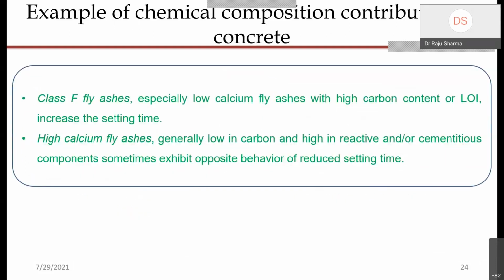Now, if we justify the chemical composition contribution in concrete of different materials, take the example of class F fly ash, especially low calcium fly ash with high carbon content or LOI, which increases the setting time, right? Because the unburned carbon is considered as LOI, and it is not at all reactive. The carbon content is not reactive, it just acts as a filler. So it's like you are making a box denser and denser, but those particles are not able to create a chemical attachment with each other, right? This is the scenario when you use a high content of LOI in any waste product. If your LOI is high, that can give you a filler effect, but that cannot give you good retention. It means your composite suddenly breaks, right?